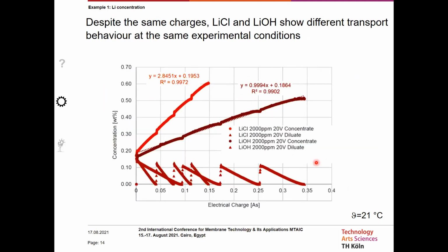Then we tested several different lithium-containing salts, which are important for the production of the LIBs, that's lithium chloride and lithium hydroxide. And we could see that they show different transport behavior, although the experimental conditions were kept stable, as we can see here. So this is the slope for the lithium chloride, and this is the slope of the lithium hydroxide. So this depends on the respective hydrate shell that is fixed to the respective ions.